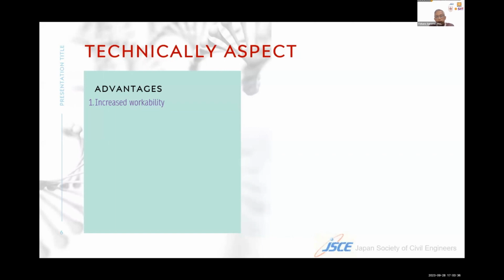In our product, some concrete that uses high volume fly ash behaves like self-compacting concrete. So the slump is very high, so this makes it easy to cast the concrete on site. Second, decreased bleeding and segregation. So the physical characteristic of fly ash can improve the cohesiveness of fresh concrete.